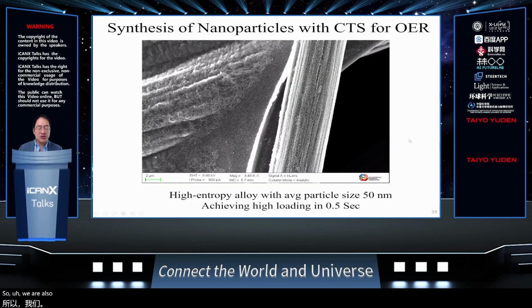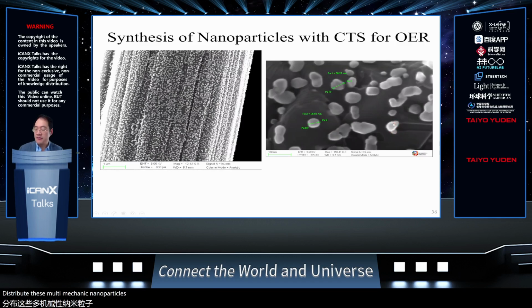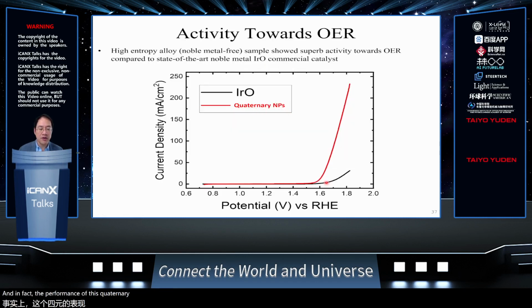In addition to these ceramic systems which work at intermediate or high temperatures, we're also making water splitters for room temperature anion exchange membrane electrolyzers. In this case, we can directly distribute these multi-metallic nanoparticles on a carbon support, and we're able to get up to 4 metals in one particle, and they're further anchored very deeply in the carbon. So you have very good binding with the carbon support, and it's used on the oxygen evolution electrode. In fact, the performance of this quaternary nanoparticle beats iridium oxide, the commercially available OER catalyst, and is also more stable than the iridium oxide nanoparticles.